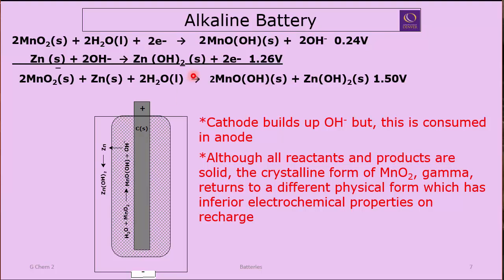But my look into the research of why this happens is it really is about its solid state, and that's back to the crystalline state, which we studied in General Chemistry 2 in the very first sections where we looked at X-ray crystallography. Manganese 4 oxide could have very different forms, and chemically they're the same material, but their physical crystal structure has a different configuration, and one of those is not as conducive to undergoing this chemical reaction as we have it drawn here.